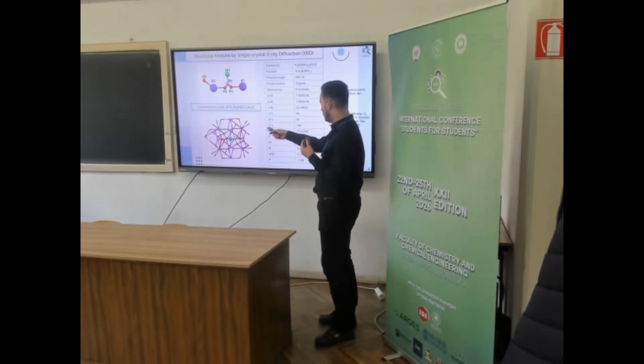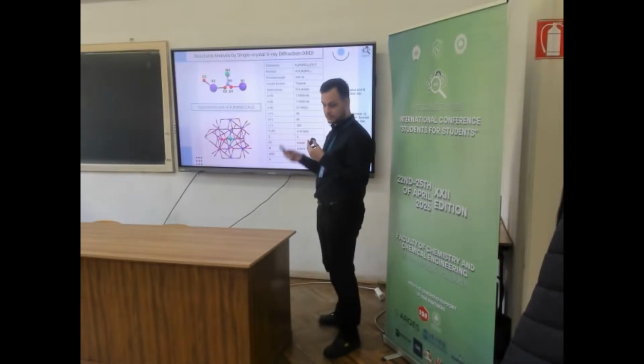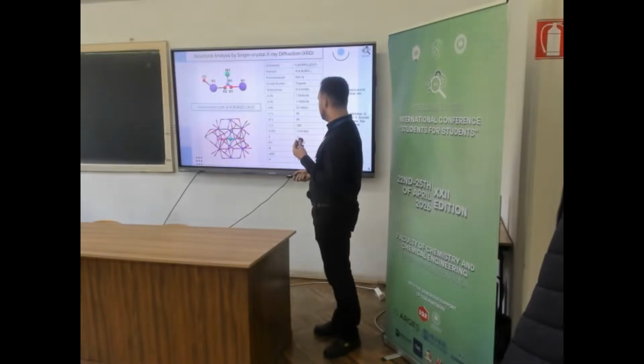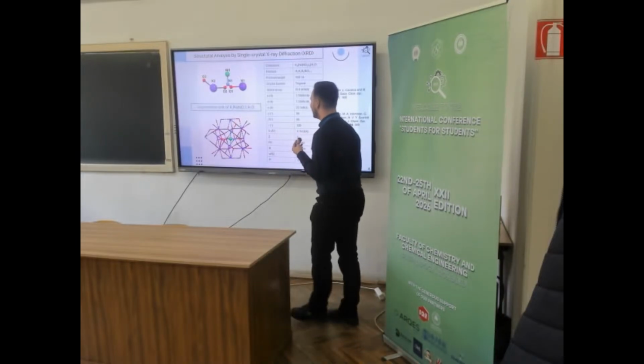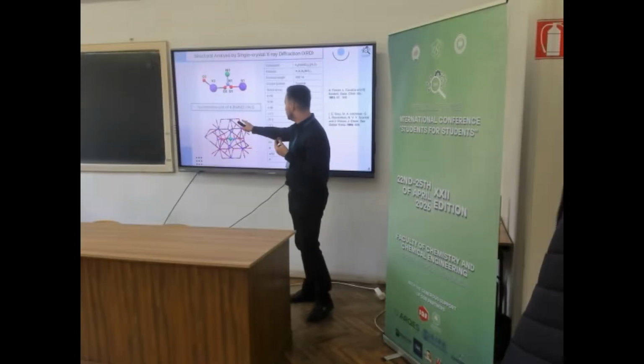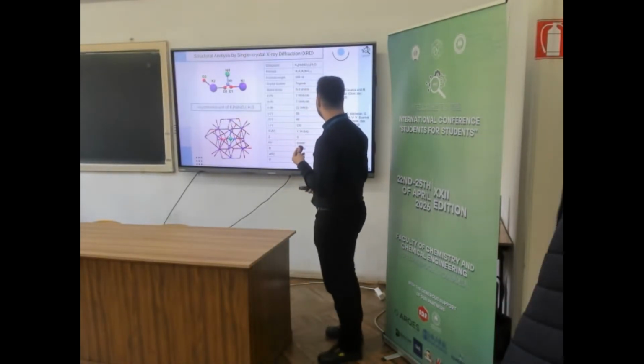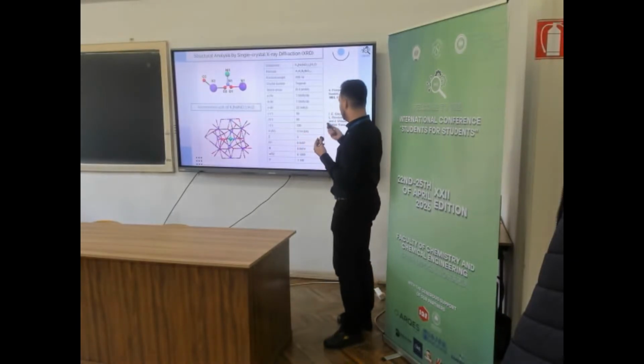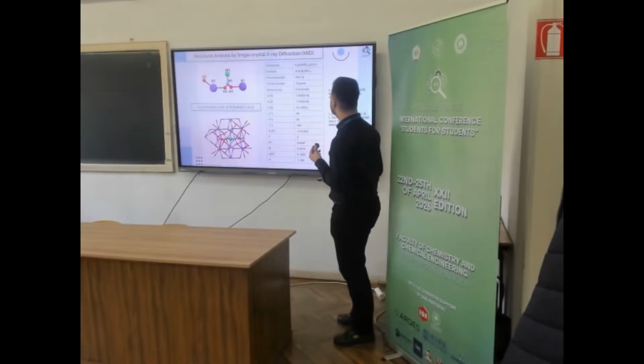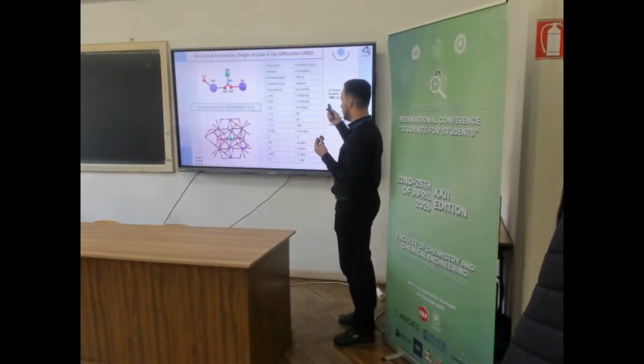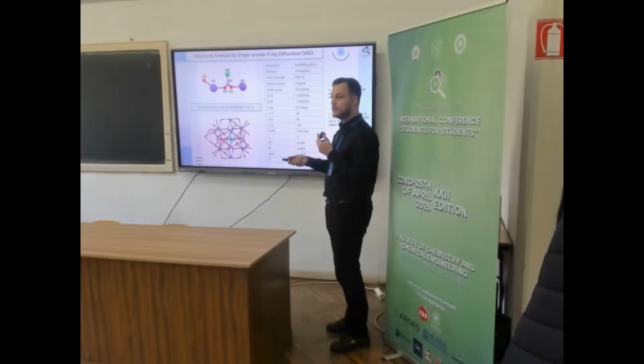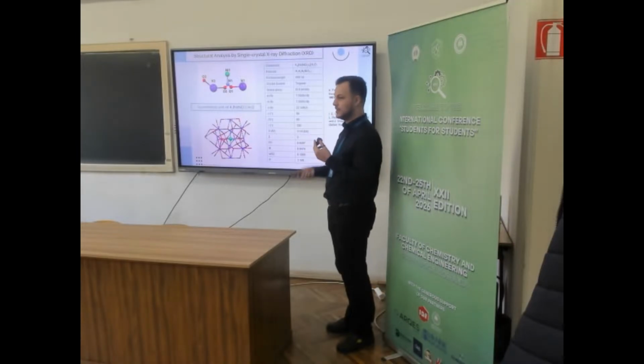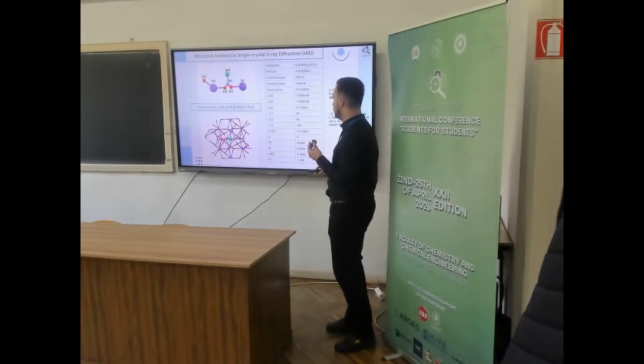If we grow this fragment, we will have that result, and that result shows us the first coordination sphere. We can clearly see the octahedral geometry, and the second coordination sphere, which shows us the potassium ions, and you can see the water being a bridge. For the experimental values, the lattice parameters, we have the crystal system. It's a trigonal crystal system, and the values of the a, b, and c lattice parameters coincide with old studies that were done on this complex, which further assures us that this is the real formula.